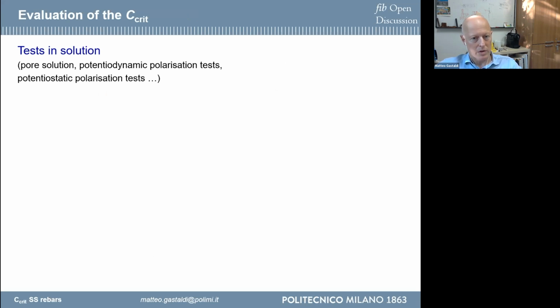So the problem is how to evaluate the critical chloride threshold for stainless steel rebar. And in the past, a testing solution was proposed, which was proposed also for carbon steel, not only for stainless steel. Testing solutions generally use an alkaline solution that simulates pore solution, and different electrochemical tests, potentiodynamic and potentiostatic tests, were used in order to evaluate the corrosion resistance and to estimate the chloride threshold for stainless steel rebar in this condition.